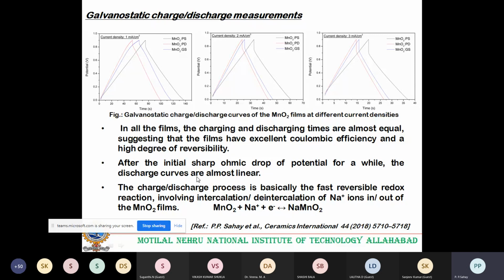The charge discharge process is basically the fast reversible redox reaction. You see, this is the reaction which is occurring there. Our film is MnO2. The electrolyte which I use is sodium sulfate, Na2SO4. So what happens? The sodium comes and forms this one. So during charging this phenomenon occurs, during discharging, back. So the charge discharge process is basically the fast reversible redox reaction involving intercalation and deintercalation of sodium ions in and out of the film. So during charging it is in, during discharging it is out. And this is the Faradaic reaction.